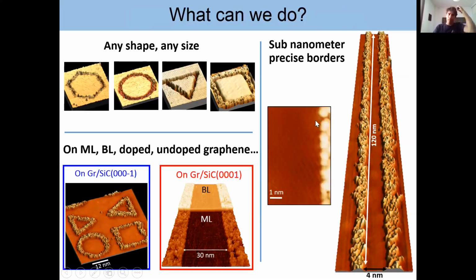And we can have quite good precision. We call it sub-nanometer precision. If we are very good, really, it goes very, very sharp. But here you can see, for example, a nanoribbon with 4 nanometers width and more than 100 nanometers length. We have been able to do 2 nanometers and more than 100 nanometers. That's what we can do. And you can see the method is really versatile and it works very well, I can tell you.